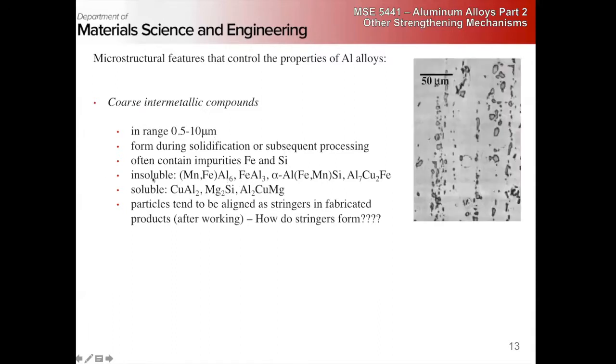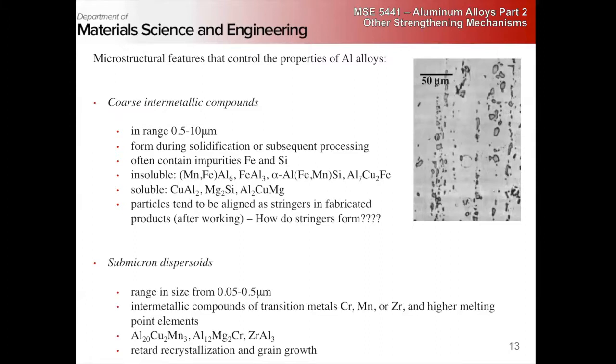intermetallics, right? And these can be classified as either soluble or insoluble. Insoluble are going to stay there until you get them above the melting temperature. Soluble has a solvus in the solid state. So that's what we mean by these.